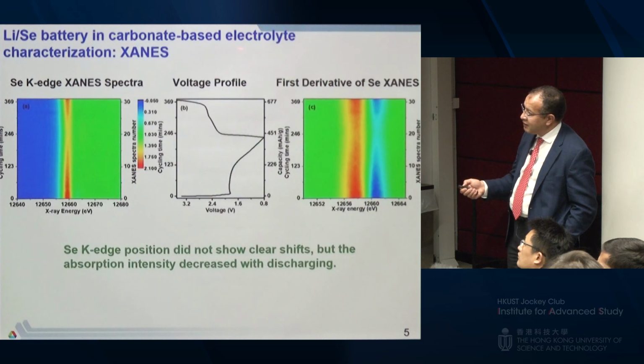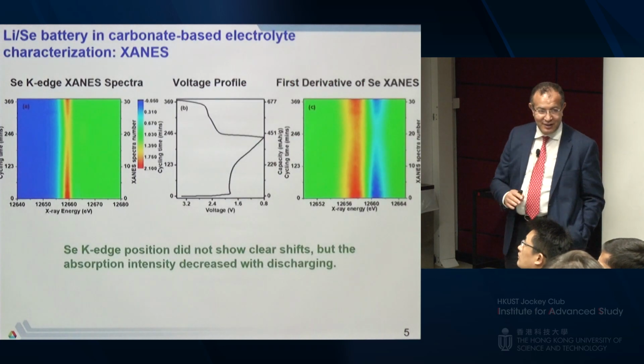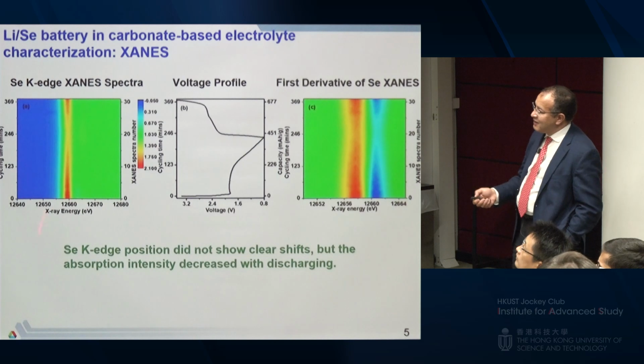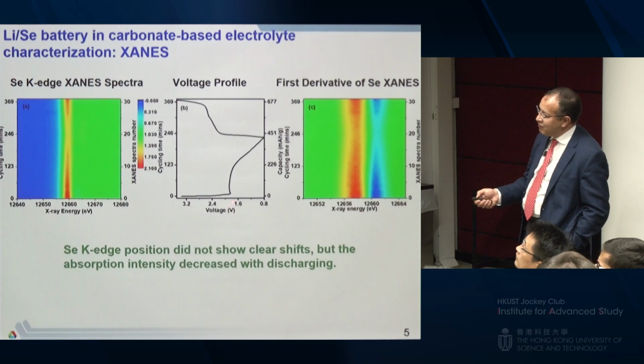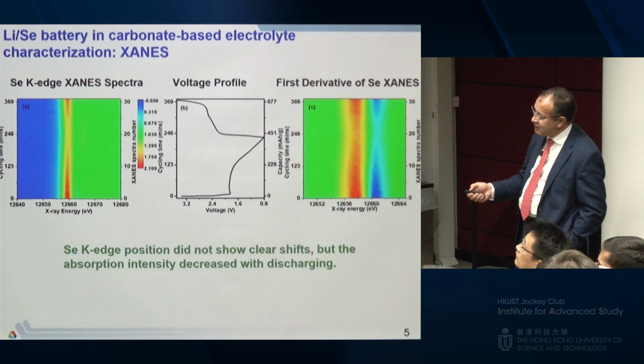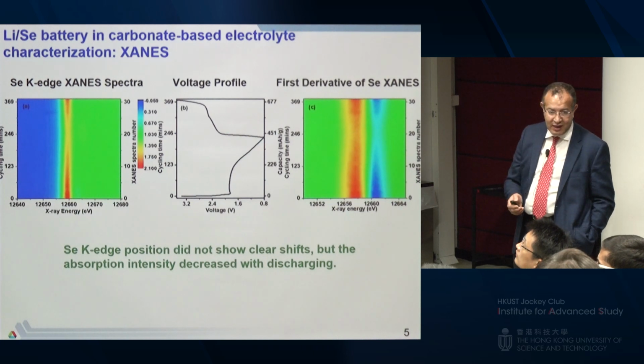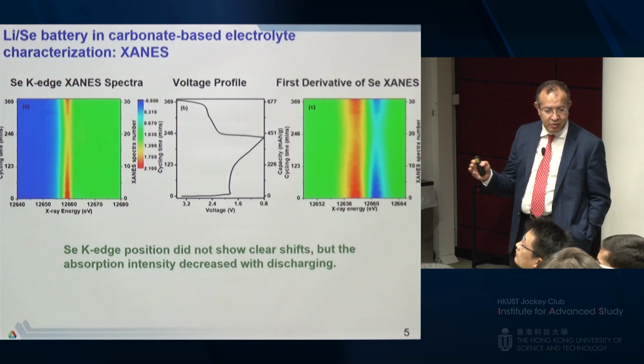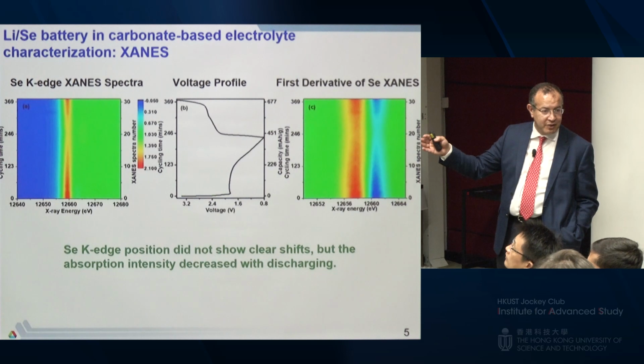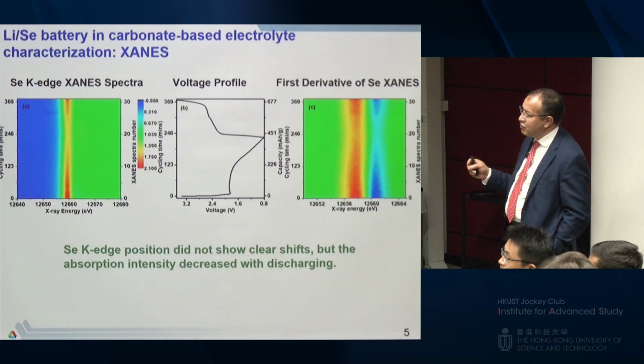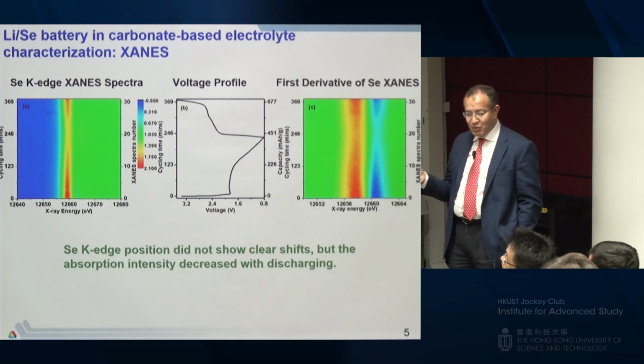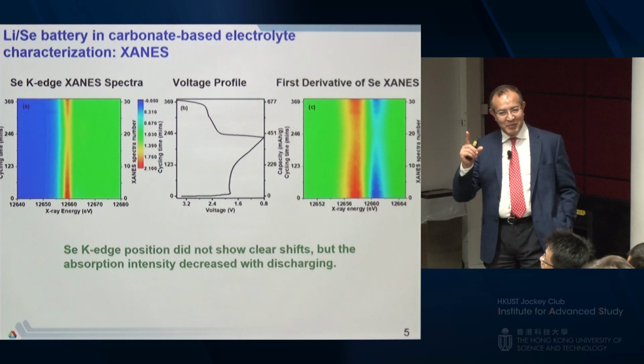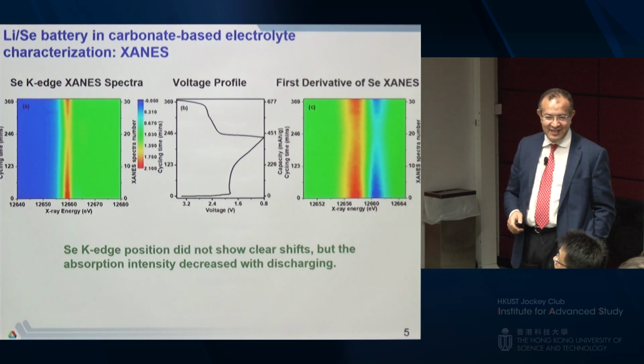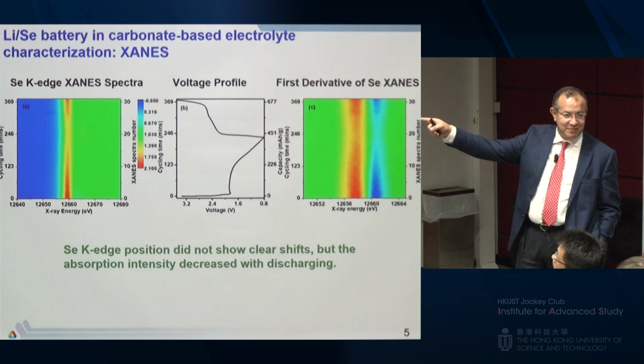Then when we ran the carbonate-based electrolyte, we saw a different story. See, it's flat. We don't see those multiple phases, but the polarization is very high. So the performance was very poor because the impedance was very high with the carbonate. Now what we learn here is that if you use a different electrolyte, the story is different. So now we have a hope. We need to find the electrolyte that can work with this new system.